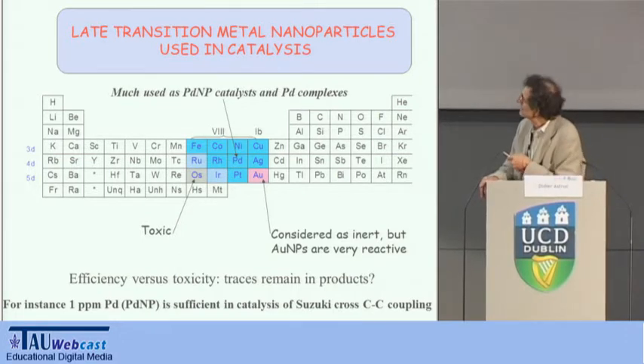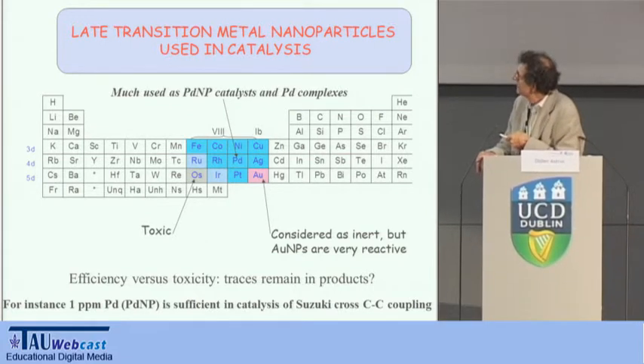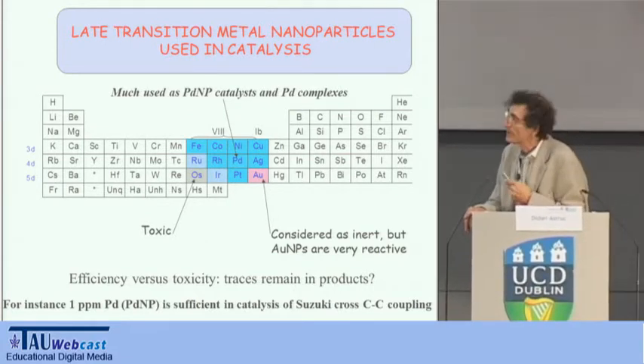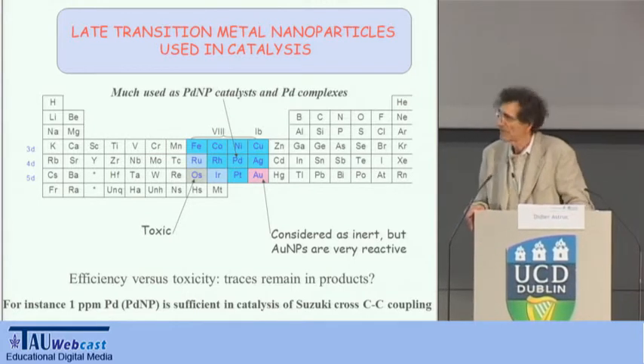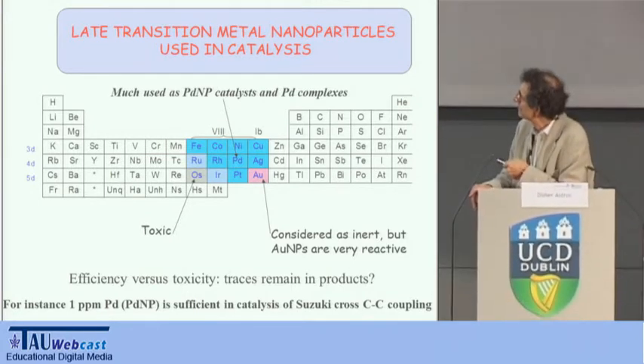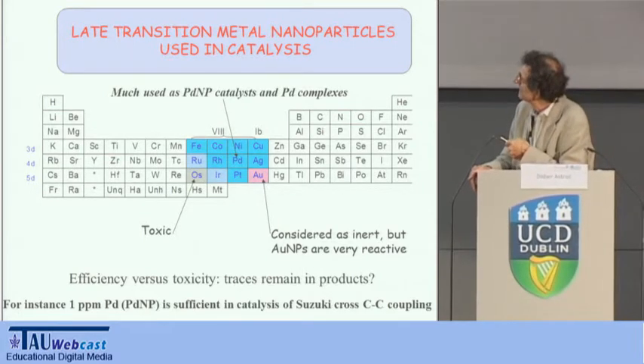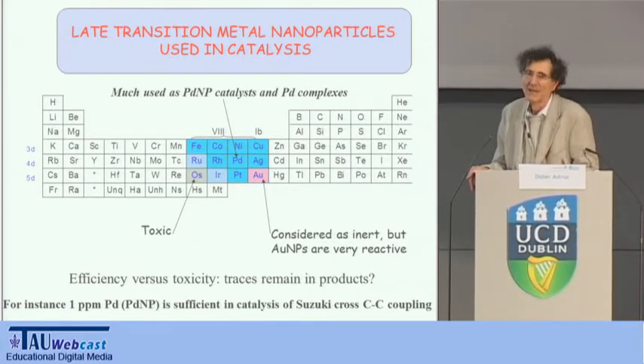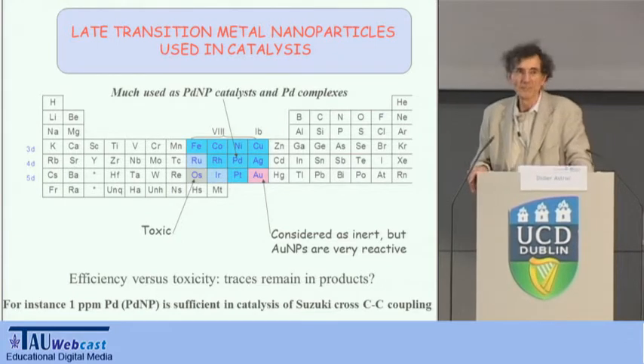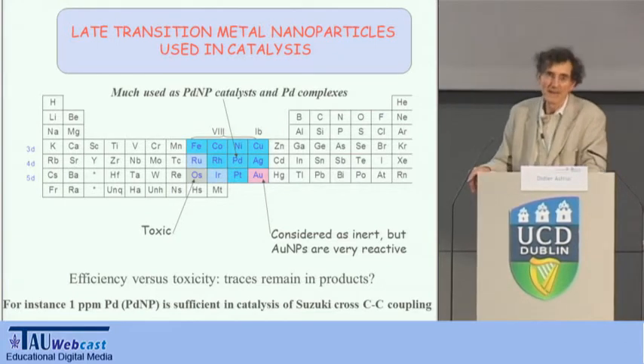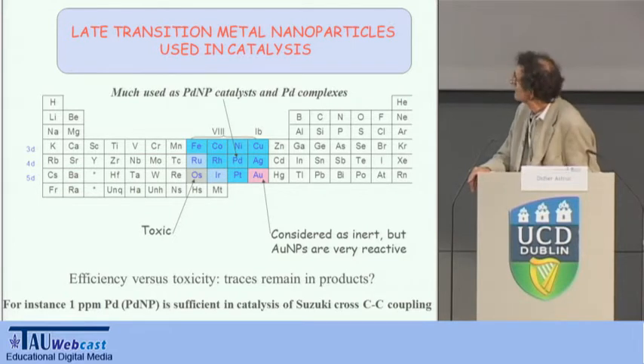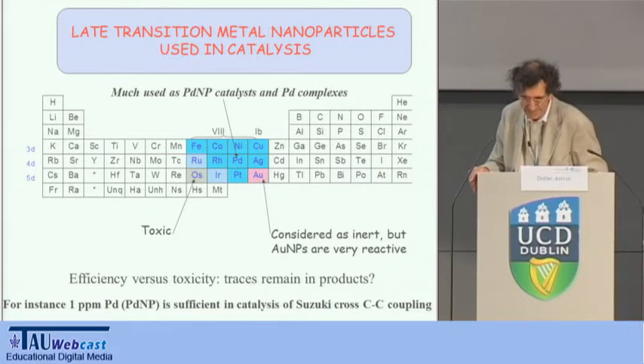So if you look at all these transition metals which are located here, everybody knows that osmium is toxic, but now we are talking about bulk metals and not about nanoparticles. Concerning nanoparticles, it's probable that all the nanoparticles are toxic. Gold may be an exception, because gold is so far recognized as being non-toxic for normal cells, at least as far as now. So the problem is to try to find a way into the toxicology of these nanoparticles.